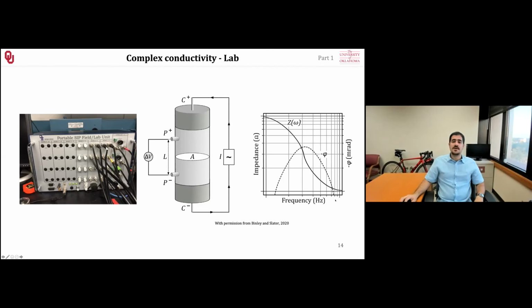measures. So what it will give you, you start measuring from lower to higher frequencies, and each of them will give you a point of phase and impedance. And when you plot everything over a frequency range of your measurements, you will get such a diagram. So ideally, you will have a peak in your phase shift or phase lag spectra, and sort of an inverse S shape in your impedance.